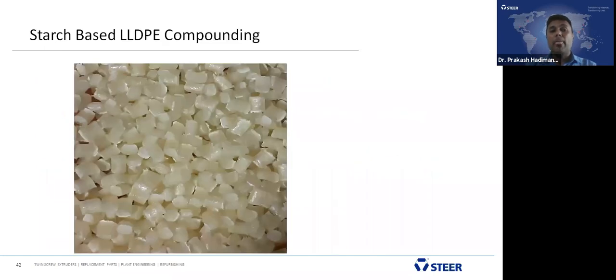And finally, we made a compound using starch-based LLDPE with 30% starch. There is no black speck, and the dispersion was good. We carried out mechanical property tests and got better mechanical properties, and also a better blown film using this compound.